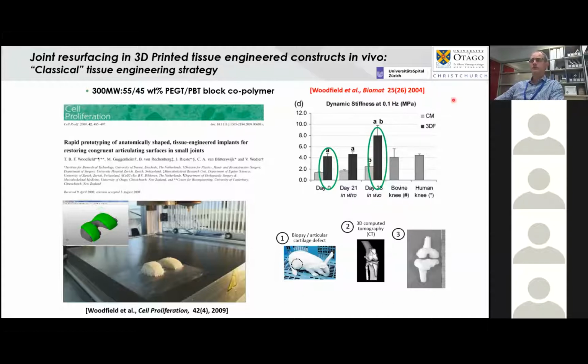It went back to some of the very beginning work we'd ever done around demonstrating a capability that we could melt extrude thermoplastic polymers, and we were very much targeting that the structure and function of those materials then match the dynamic stiffness of articular cartilage, and that when we also formed tissue over 28 days in vivo, we could get even an improvement in mechanical properties. So we're trying to essentially make sure that the structural component of these scaffolds had an anatomical shape, were porous, and were promoting the best possible microenvironment, so that when we placed cells within that microenvironment, we could get differentiation.